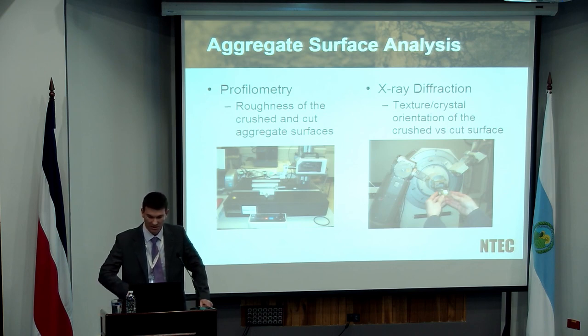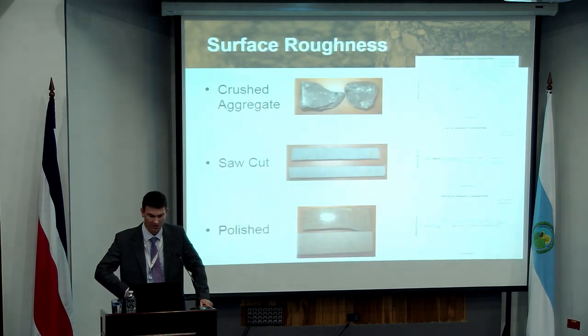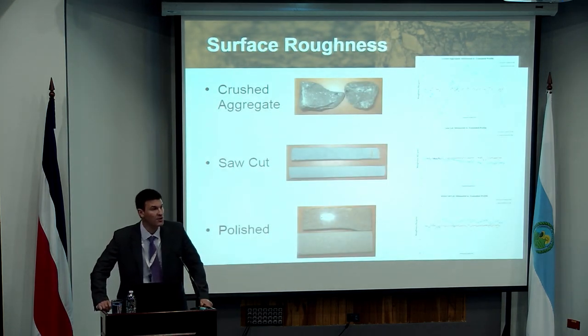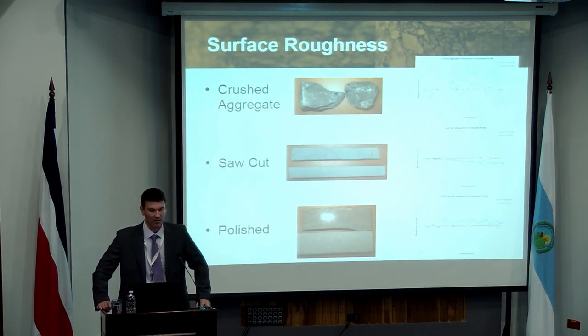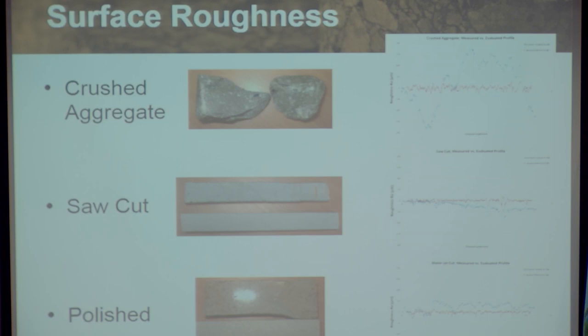So profilometer, X-ray diffraction on the materials, and a few examples. So we looked here at obviously the crushed aggregate that we would obtain from a normal asphalt plant. We looked at our substrates, and we looked at two different conditions of our substrate. Some of them were simply cut and then tested. Some of them were polished using some form of sandblasting.